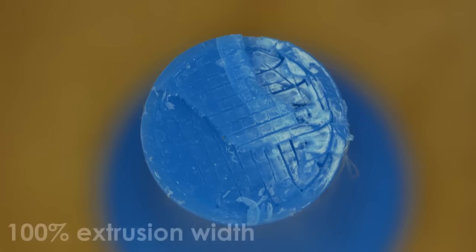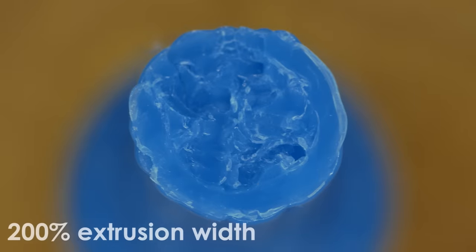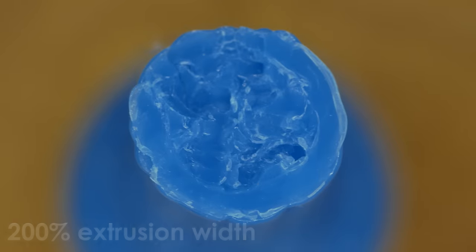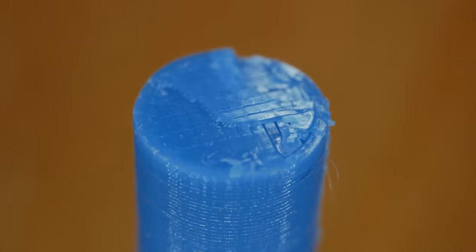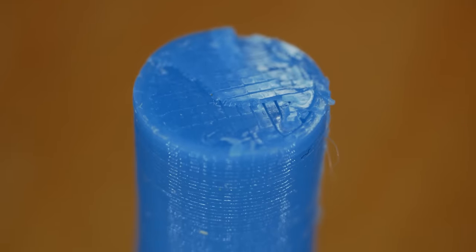At lower extrusion widths, the crack planes are only over one or two layers, and they become more ununiformly the more material is squished out. Another indication that we're on the right track.